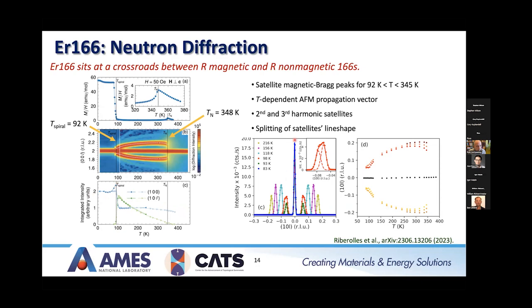In addition to these main features, we also observed some fine structure in the diffraction pattern, which I'll just mention for now. You can find some more details in this arXiv post. Basically, these satellite magnetic Bragg peaks appear to be what we're calling split. They don't correspond to just a single Gaussian line shape. They're actually the superposition of either two or three Gaussians, and the number of Gaussians changes with temperature.